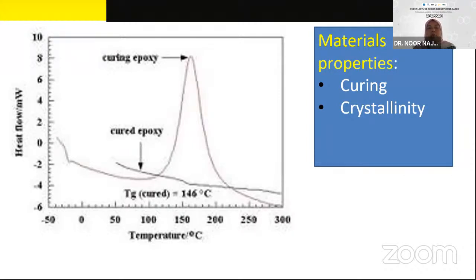the one more piece of information that you can get is material properties, whether it is the curing process or the crystallinity process. For the curing process, when you run your sample and you get a baseline, it means that your sample is fully cured. If you send your epoxy or thermoset polymer sample and you get this kind of peak in the DSC analysis, it means that your sample is still under cross-linking process. For thermoset polymer, if your sample is still under cross-linking process, it is not advisable to produce a product from that. You need to make sure your sample is fully cured, and then it is good to produce a product from it.